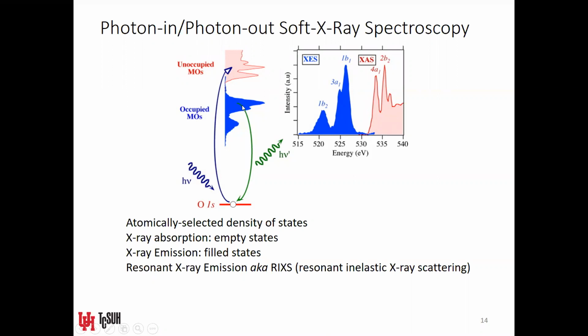If you also measure the downward transition that occurs to fill this hole that you've created, you can detect the outgoing or the accompanying radiation, okay, in your experiment using the right type of detector. And that process of emitted radiation is known as, well, it's X-ray emission, but the technique is known as X-ray emission spectroscopy. So this figure is showing both how we do X-ray absorption spectroscopy and how we do X-ray emission spectroscopy. The plot to the right is meant to show you that the X-ray emission process will give you information about filled density of states or occupied density of states in blue, whereas the X-ray absorption process would actually give you information about the conduction band.